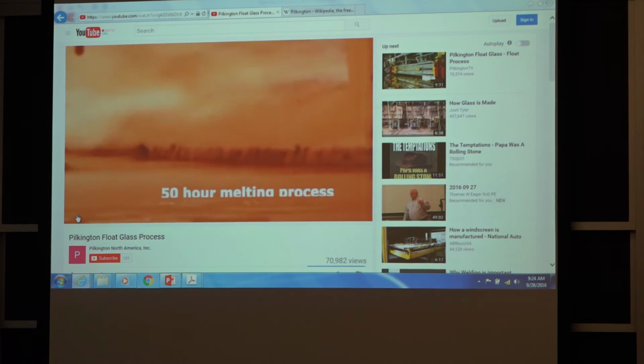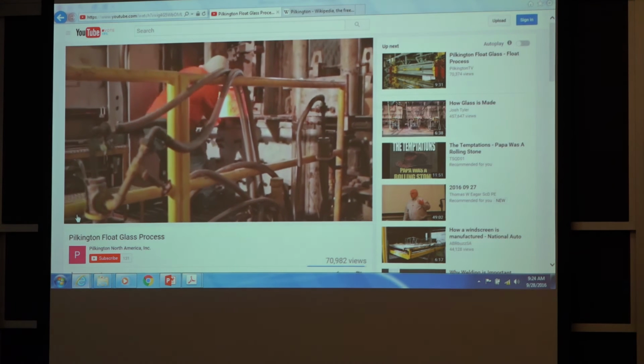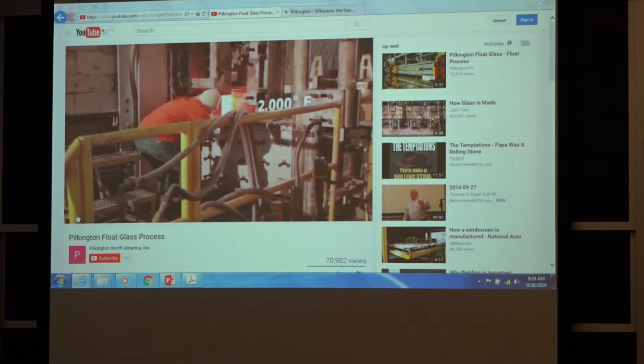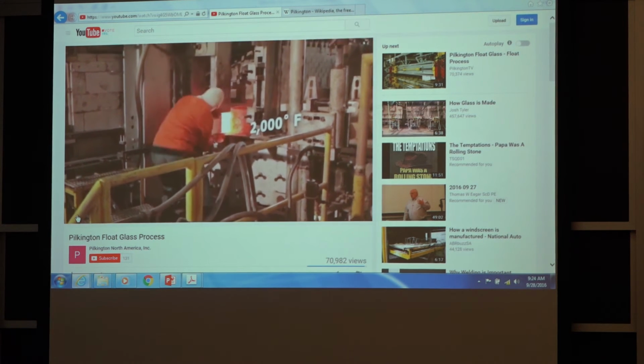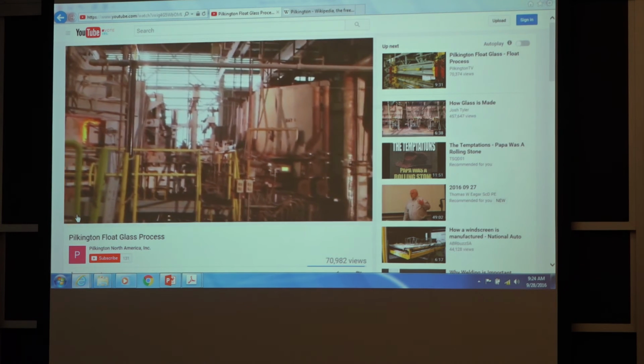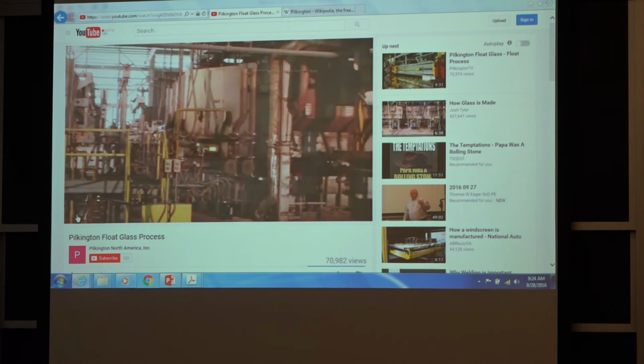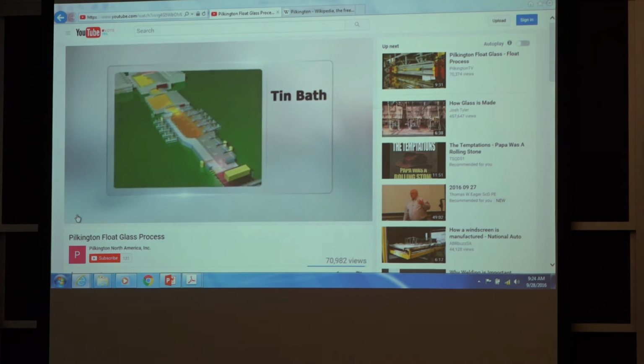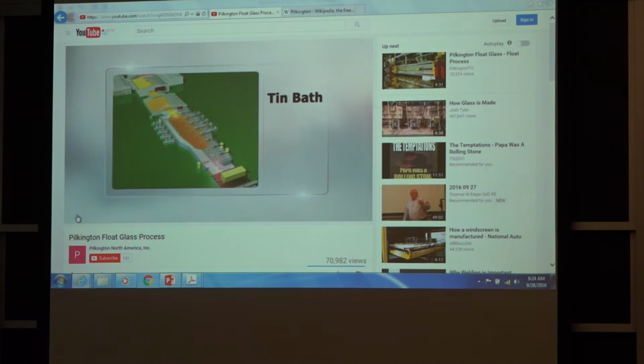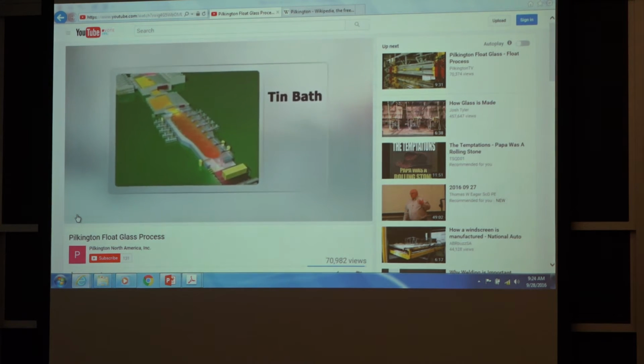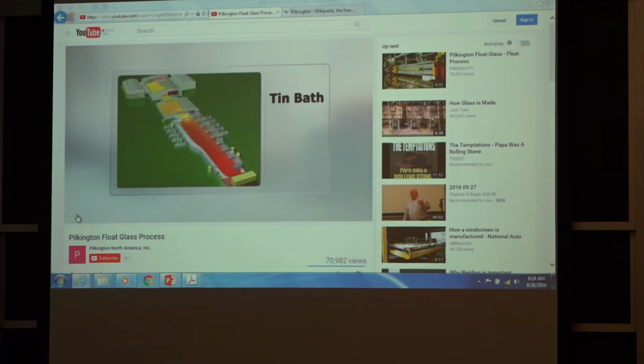This continuous melting process can last as long as 50 hours. The glass leaves the conditioning end of the melting zone at a temperature of 2,000 degrees Fahrenheit through a narrow canal where it passes to the heart of the process, the tin bath. Molten glass enters the tin bath and floats on top of the more dense molten tin, like oil floating on water. This is what I discussed earlier.